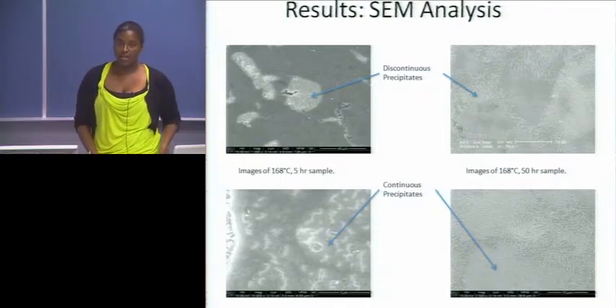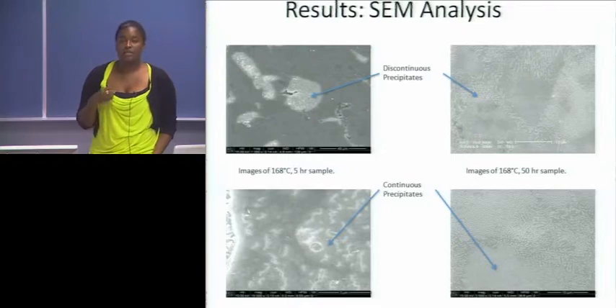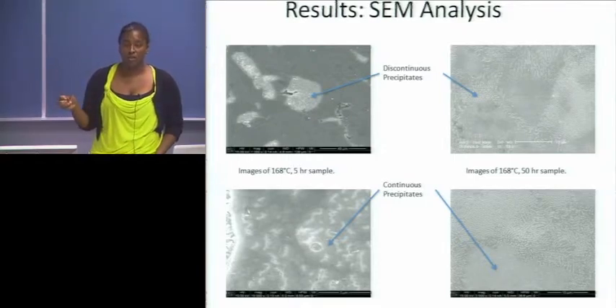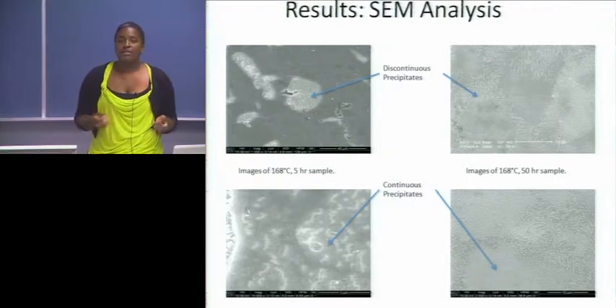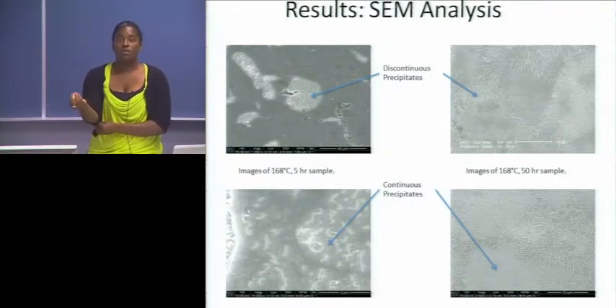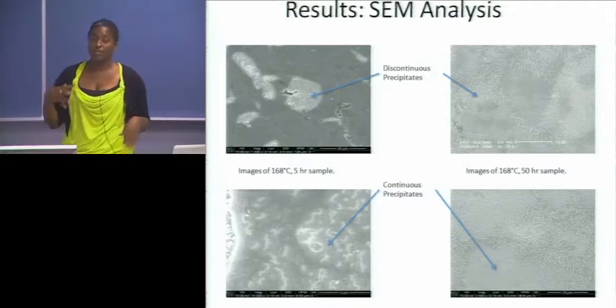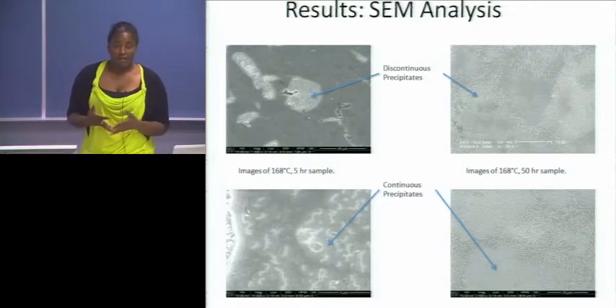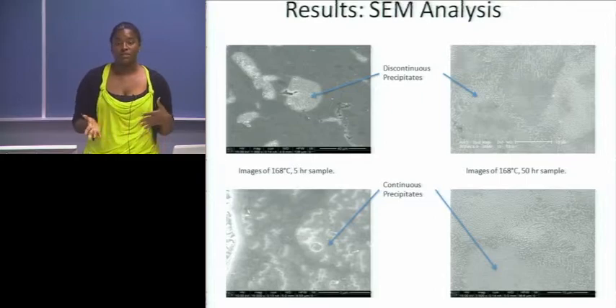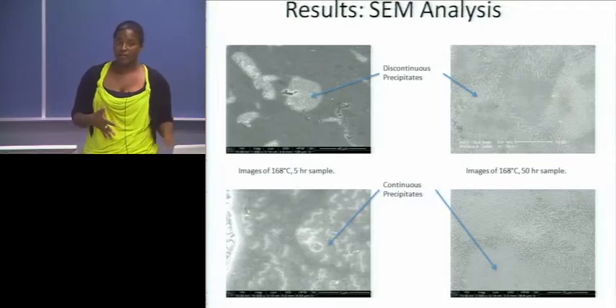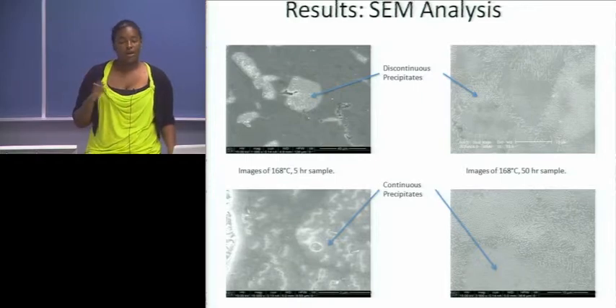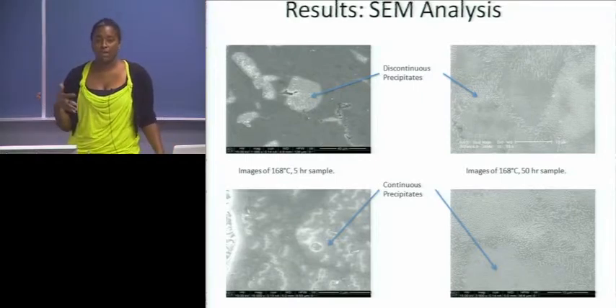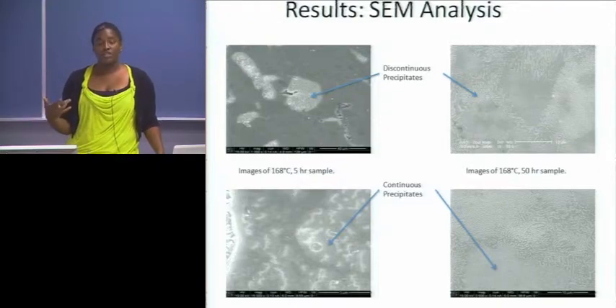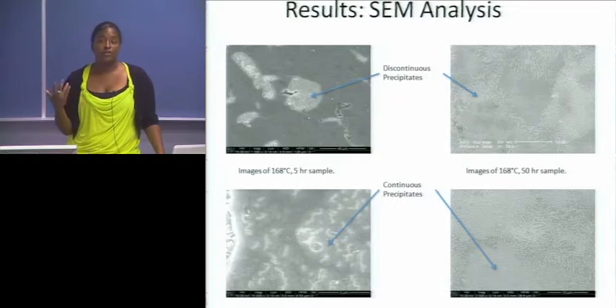hardness and tensile testing, and with the hardness testing, I took 8 to 10 points along the cross section of the sample, and I was looking to see if there was any difference between the hardness on the surface of the sample or in the center of the sample, just because some papers have found that there are more precipitates on the surface, which is why the hardness is higher at the surface. But for my samples, the hardness varied from surface to center, so I couldn't make a conclusion on that. But what I did find was that the hardness did increase with aging time. So I saw that hardness did increase, so the precipitation microstructure did have an effect on the hardness.